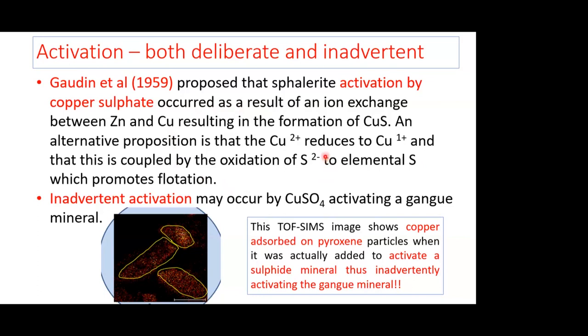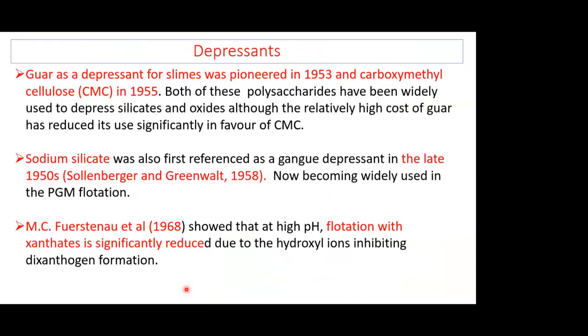And I'm not going to dwell on this, but a student of mine a number of years ago, when we were using TOF-SIMS to look in the platinum concentrators in South Africa, copper sulfate was widely used, and we were able to show that the copper sulfate actually activated pyroxene particles, and the TOF-SIMS showed it beautifully by showing how the copper was present on the pyroxene particles, activating them, which is certainly not what was wanted.